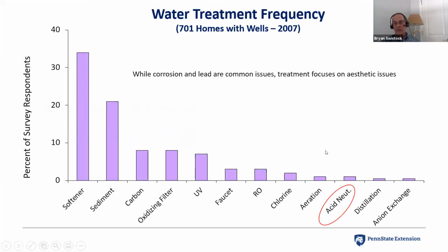What we see, however, is that those systems are not installed very frequently. In Pennsylvania, we find only about 1 or 2% of people have an acid neutralizing filter, despite the fact that corrosivity is about 60% of the private water supplies. Water treatment is focused very much on aesthetic issues like softeners and sediment filters, and much less so on health issues like bacteria with UV lights or RO units or chlorine systems. So that's one of the real disconnects we have between treatment and problems, is the treatment is very focused on aesthetic problems because they're visible and people can see and taste them, and less so on some of those health